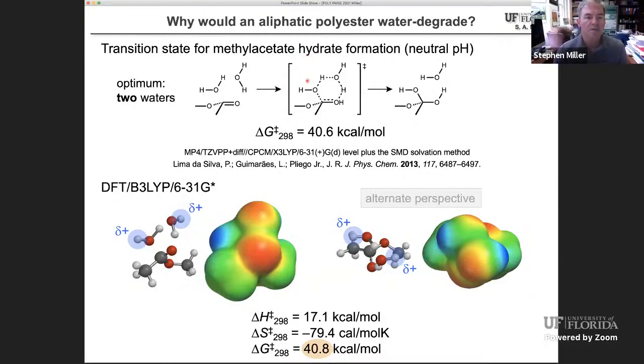So we looked up some literature about the hydrolysis of a very simple ester here, methyl acetate. You can study its hydrolysis. You can undergo the first step of hydrolysis, which is hydration of an ester. That first step is to make this hydrate of an ester, and that seems to be the slow step, generically speaking, on the pathway to full hydrolysis.